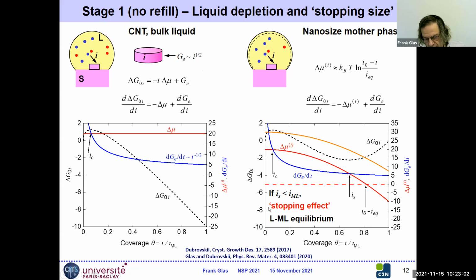So this we call between us the stopping effect. We might reach this. And this is something which has been, of course, studied for a long time theoretically in the field of nucleation theory in small systems. But of course, there are very few experimental verifications. So that's what our experiments in nanowires allow us to do. And it also had not been considered in the field of nanowires. So again, it's Professor Dubrovskii in 2017 who thought about considering such a phenomenon in nanowires, and that's this stopping effect.